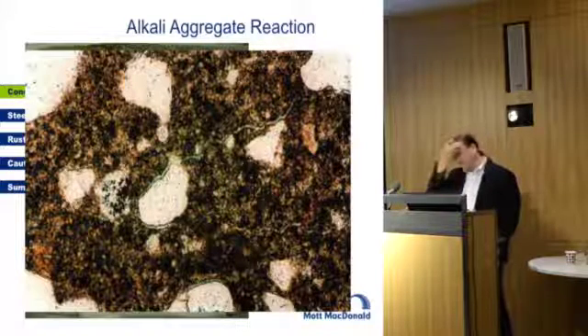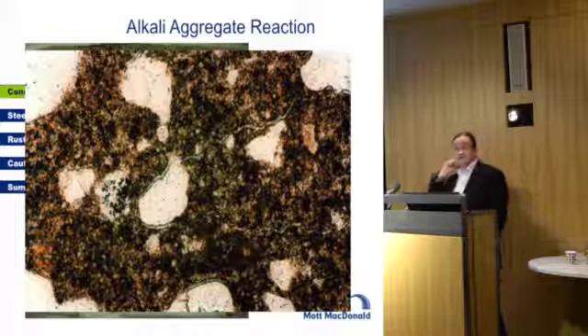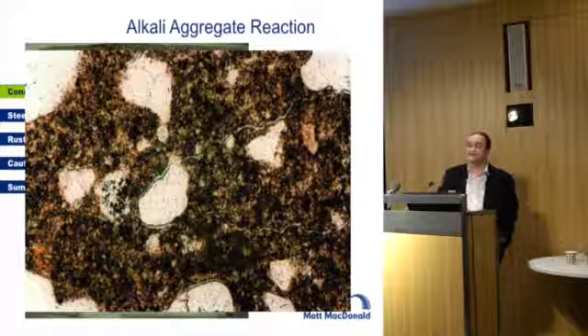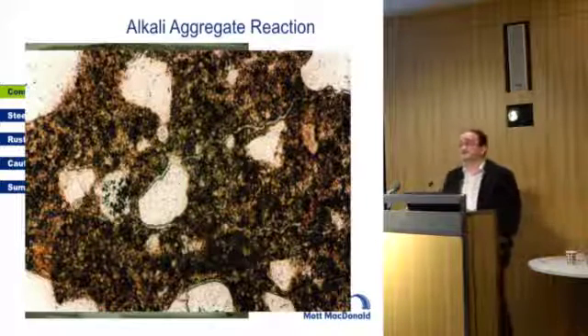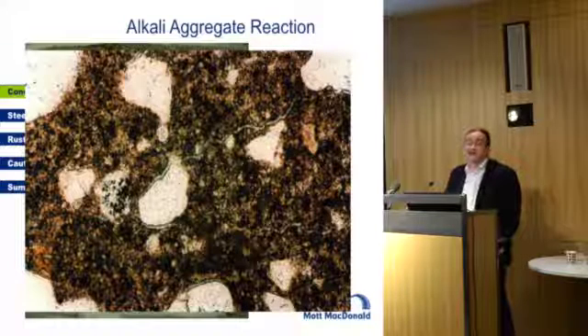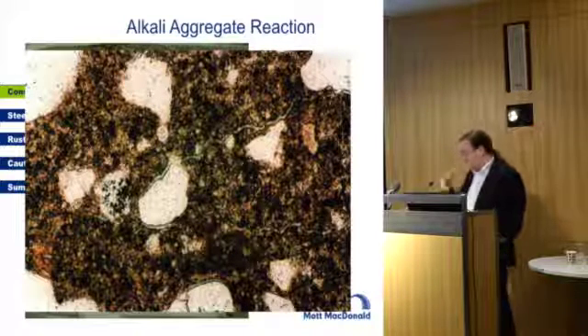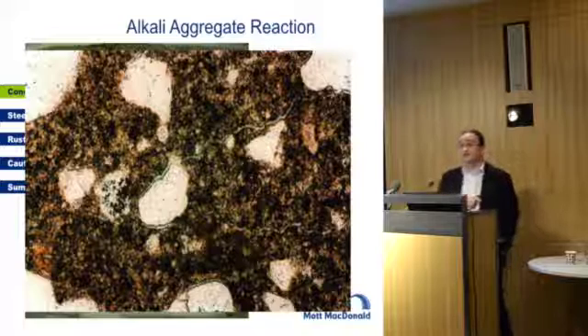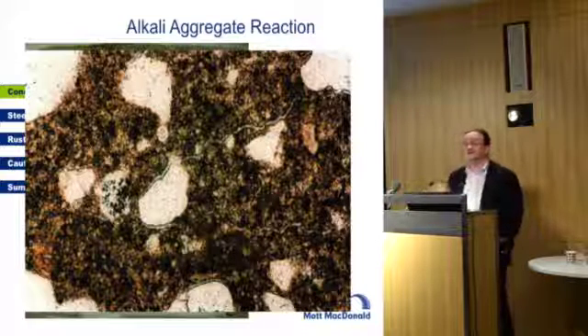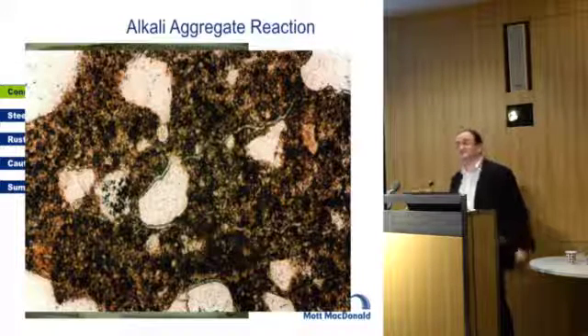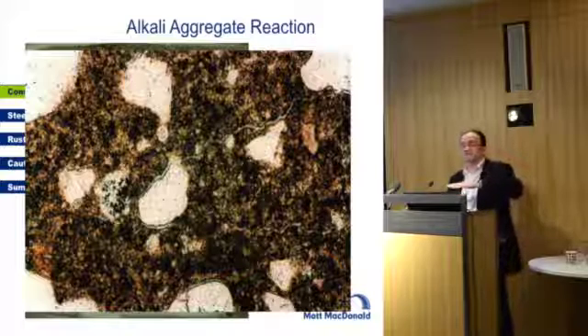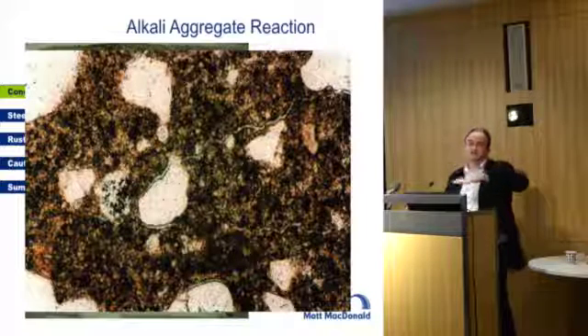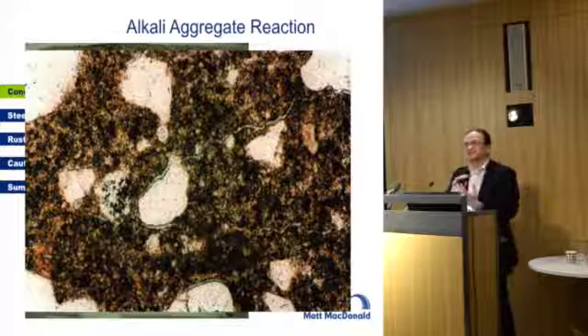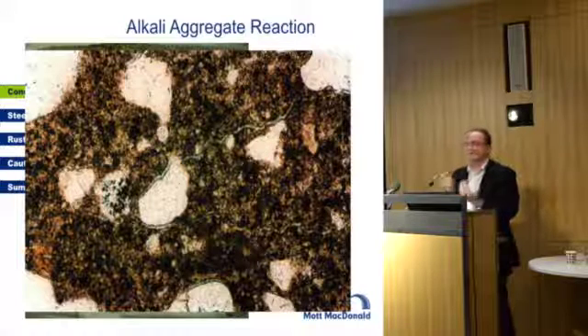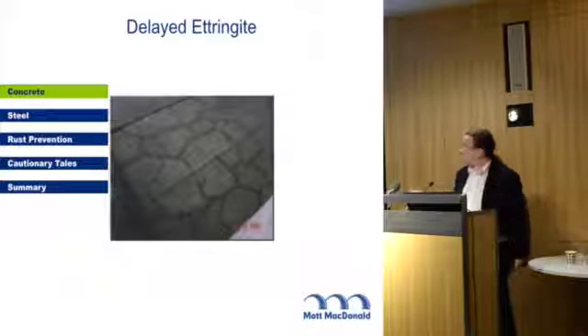Delayed Ettringite formation. Sounds like I've been a bit cleverer in the name, but Ettringite is something that happens when cement gets produced. And when you cast concrete, you get Ettringite. Delayed Ettringite formation is when the formation of Ettringite gets delayed. Normally this is because the mix has got too hot during the curing process. If it gets above 70 degrees C, you kind of muck up the cement reactions a little, so it gets delayed. And you get cracks.